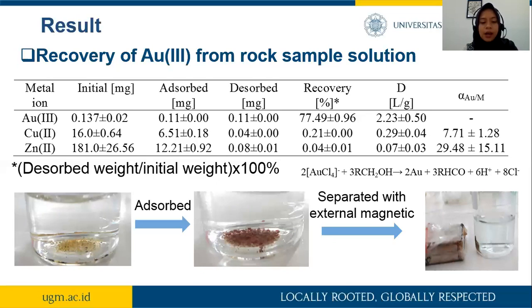Chitosan in the adsorbent MMSC contains amino groups and can be protonated to form the cation of alkyl ammonium. So the metal ion Au3+ can be adsorbed onto our adsorbent. There is the picture. The color change of the adsorbent after the adsorption process goes from yellow to reddish brown. The color change indicated the adsorption and the reduction of Au3+ to Au0.